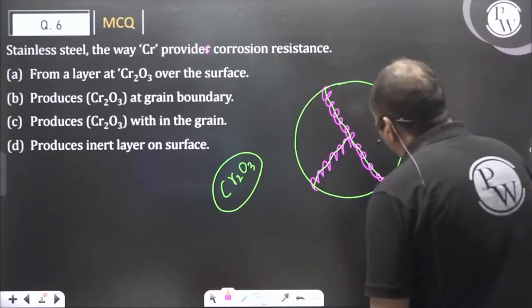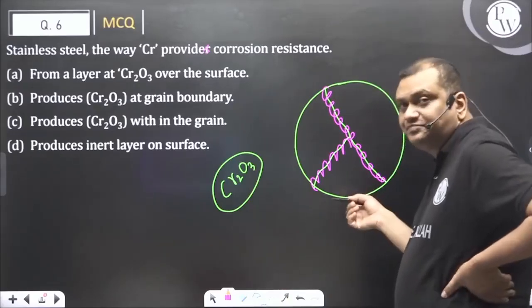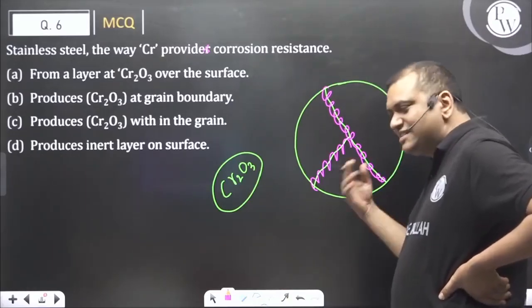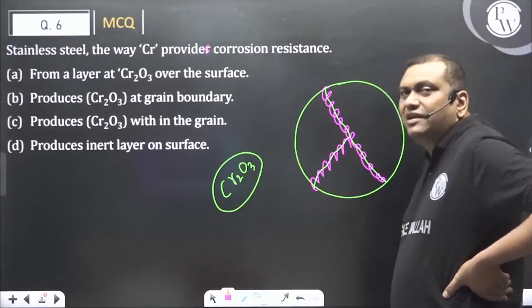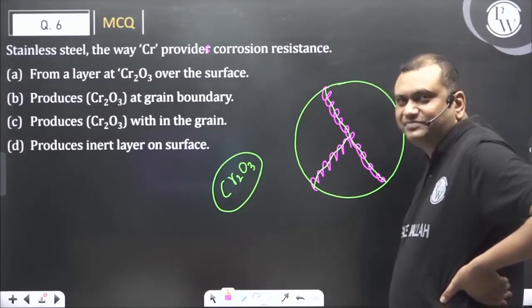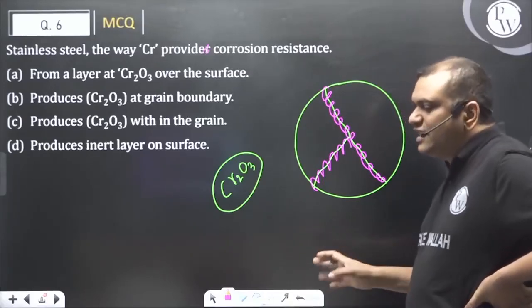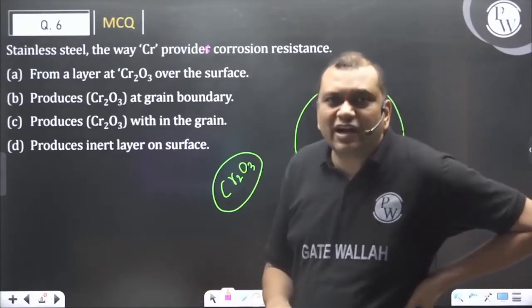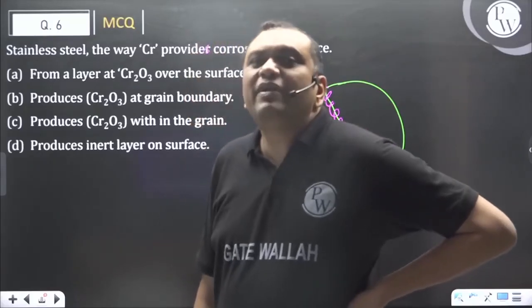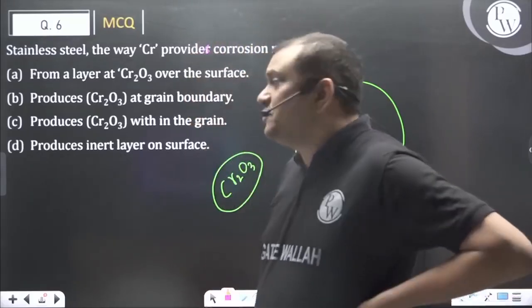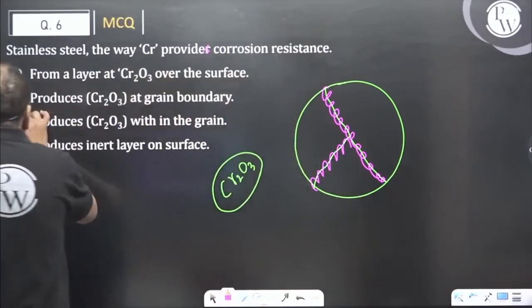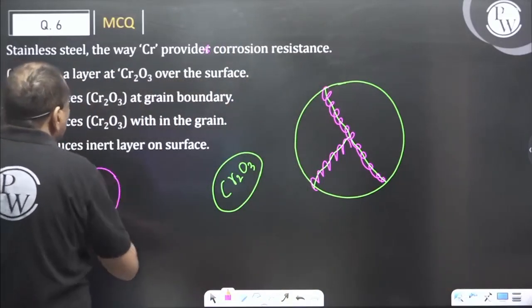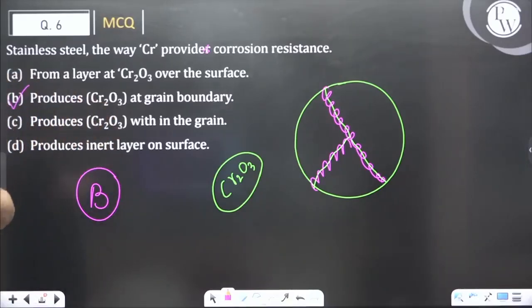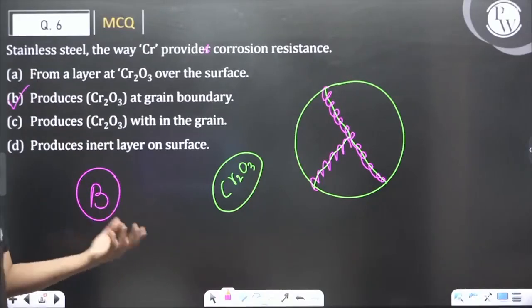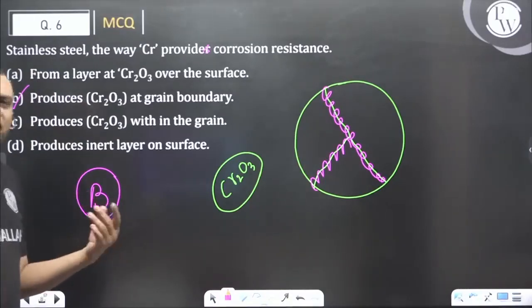So at grain boundary, bond length will be slightly larger. Larger the bond length, easily bond can break. That's the reason corrosion always starts at grain boundary. But what the Cr2O3 has done, it formed a protective layer over the grain boundary, preventing the grain boundary atoms from the attack of atmospheric gases. So B. It doesn't produce surface coating of Cr2O3 over the surface. That is not correct. Okay. So it produces protective layer at the grain boundary, because grain boundary atoms were the first one to be attacked.